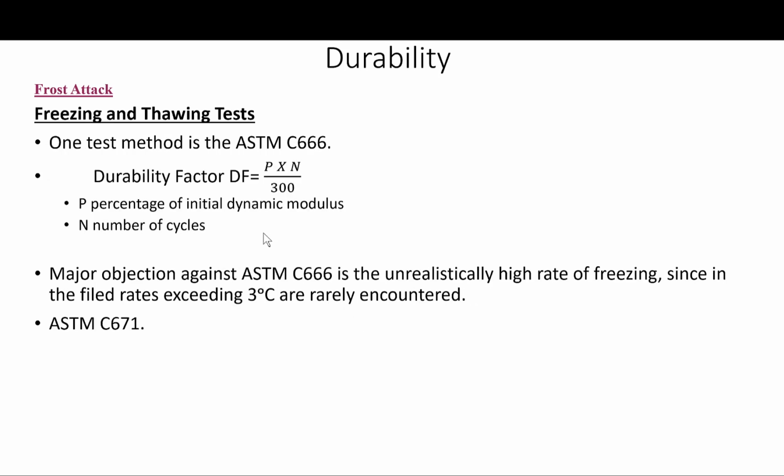Okay, the standard method of test is described in ASTM C666. This prescribes a cooling and heating cycle between 4.4 and minus 17.8 degrees Celsius, between 40 and 0 Fahrenheit, to be completed in 2 to 5 hours.